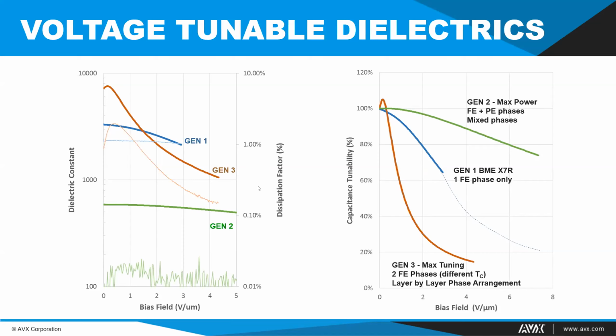So a while ago, we embarked on a program where we were able to demonstrate different materials that had a variety of different voltage coefficients and therefore different applications. We had a Gen 1 material, and I'm referring to the right-hand graph here, where we had an X7R material and looked at its typical behavior. We found it to be a little bit steep in terms of voltage coefficient, and the material was somewhat lossy too. So a new composition was derived, and you can see that it has a much lower slope to the voltage coefficient. If you refer to the graph on the left, you can see that the dissipation factor, the smaller curve here, although the K of that material is smaller, the dissipation factor is much lower, and yet we can still get some tunability out of that material.